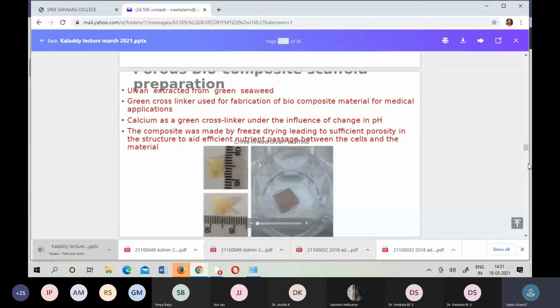So we use calcium chloride solution of 0.1 M or close to that concentration. We made sure the total alkalinity or the pH of the solution is close to 9. The solution is pH 9. Then we pour it in the small cubical structure and use the freeze drying method. When we do that, we get small cubes of whatever size we choose, but it has a lot of pores. These pores are developed because we are doing this freeze thaw method of separation.